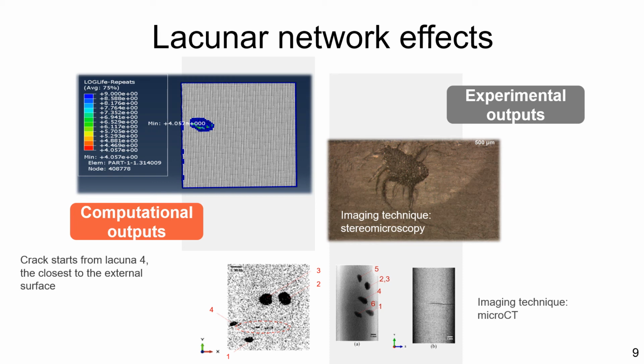Fatigue tests show a clear effect of the lacunar voids on sample life and on damage propagation. The visualization of the fracture specimens shows that in absence of an external notch, the crack starts from lacunae, while in presence of the notch, the crack starts from it and encounters lacunae, as its path is influenced by lacunar arrangement. Sample toughness and crack patterns are significantly influenced by the presence of different lacunar networks. The starting point of the crack could be predicted by numerical models validated by means of microcomputed tomography analysis.